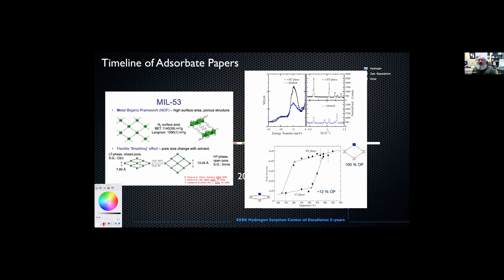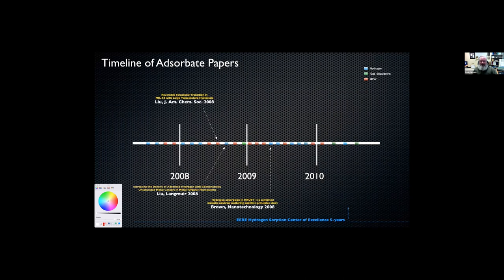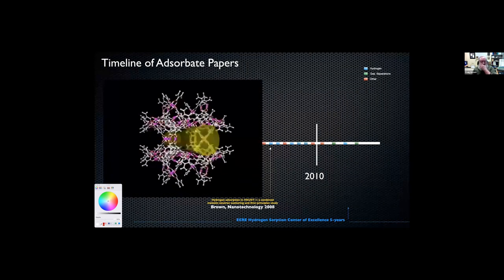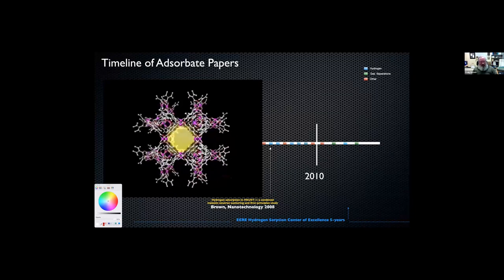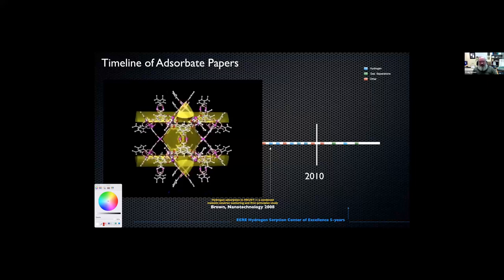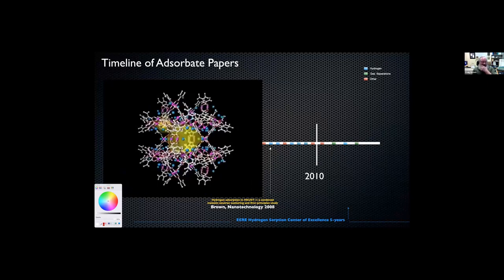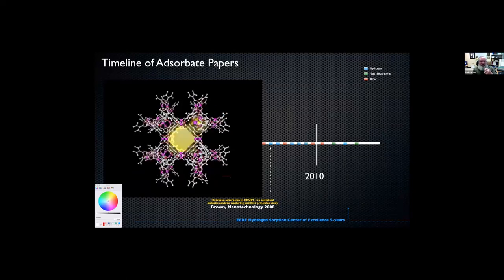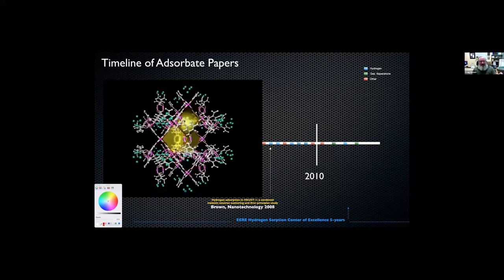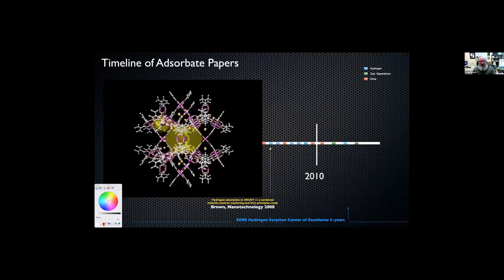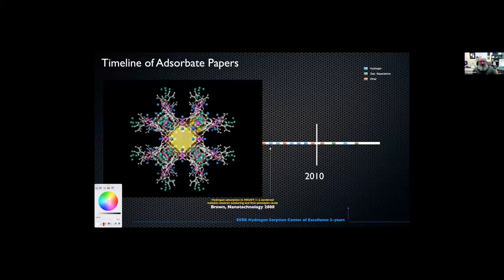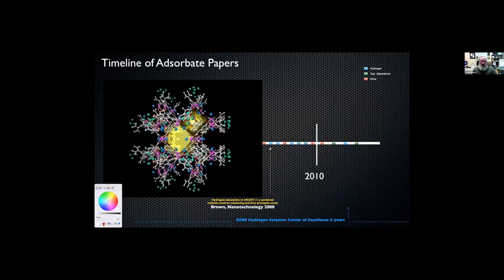But the difference between the blue and the black curve show the difference between the open phase and the closed phase. And if you integrate those phonon areas, you end up with the picture at the bottom that illustrates what we could determine from powder diffraction. I think in 2008 was like our opus on looking at hydrogen and its interaction with open metal sites. We did the crystallography previously with Vanessa Peterson and Yun Liu, where we located hydrogen at the copper paddle wheel, inside the octahedral window and inside that octahedral pore. And you can see those three different hydrogen sites in this molecular view.